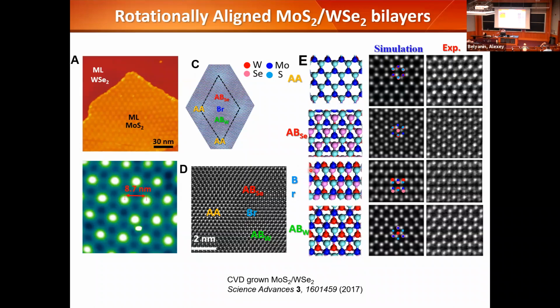And many other regions are what we call the bridge region. You don't have a perfect threefold symmetry. Not only that, because the semiconductor energy level is determined by orbital hybridization, and the top and bottom layer atoms are aligned differently as you shift around the Moiré supercell, the band structures are different as you move from one point to the next in the Moiré supercell. So this picture is a topography picture, which shows you the spacing between the layers actually changes periodically. But I can also build a picture that represents the electron local density. These bright points are the points where electrons tend to naturally puddle. Okay. So I already created a canvas of material where I define locations where electrons would like to sit preferentially.